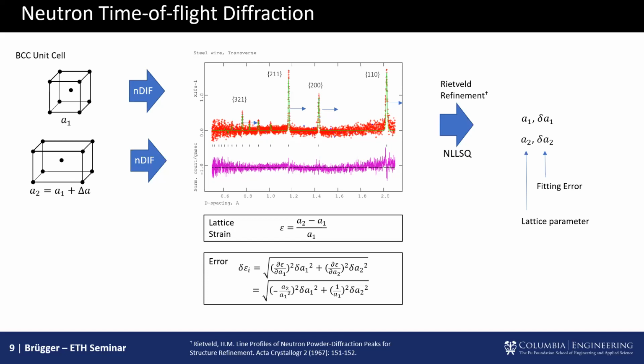Right. So it's a very good question. When it comes to residual stress mapping, the power of time of flight diffraction, or diffraction in general, is that we can deconvolute the plastic from the elastic domain, because essentially we're only measuring elastic strain. So we're measuring the truly elastic strain potential, the lattice spacing of your system.